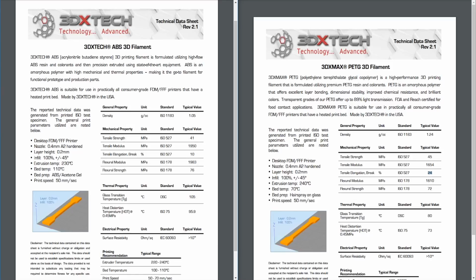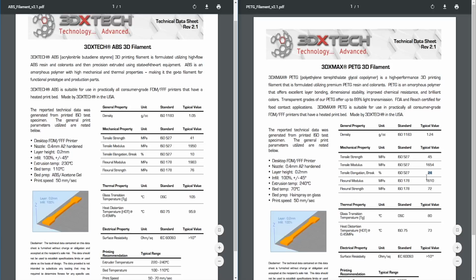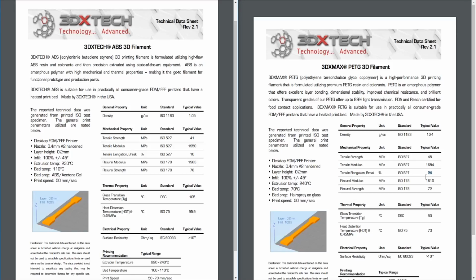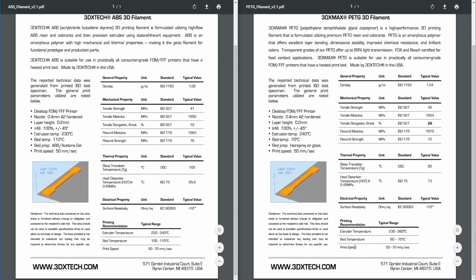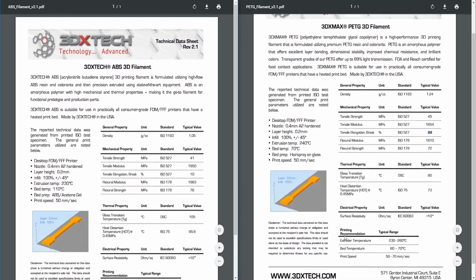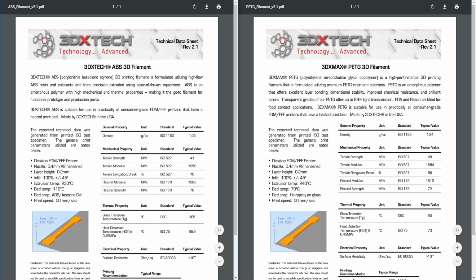Okay, so what about... It looks like it's a middle ground between ABS and PLA as far as the temperature control, but it has 4 times the flex of PLA and 2.5 times the flex of ABS. But other than that, similar setup here, except for the glass transition temperature. Also pretty similar printing. So if you could print ABS, you could print PETG.